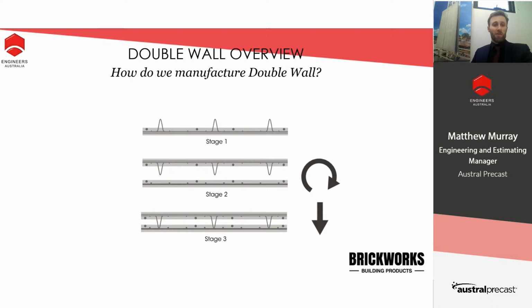Once that has reached 20 MPa strength, that first shell is taken out of the curing chamber, put onto our pallet flipping mechanism, and inverted 180 degrees. Then the second shell is poured with the reinforcement in the second shell before the 2 shells are joined together.